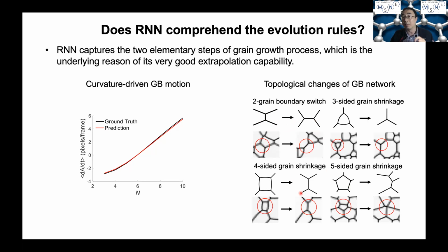So that means the model is able to learn all these local evolution rules from the training data set. Right? So combining these two steps, you can reproduce the grain growth process, and we think that's the reason why the trained RNN model is capable of doing the extrapolation into larger systems, longer times, and also in some foreign microstructure that the model has never seen before.